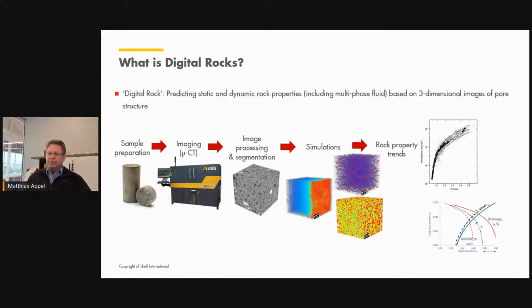And then these rock properties are upscaled again for the entire core plug and hopefully even to a larger scale to be comparable to the reservoir properties. And what's shown here is the classical porosity-permeability correlation that is used and really populated with individual measurements to derive a trend, which then can be used for the field study, or a plot of relative permeabilities, both drainage and imbibition curves, where the digital rock results are then compared with the actual experimental values.